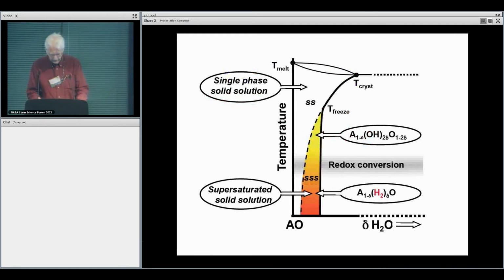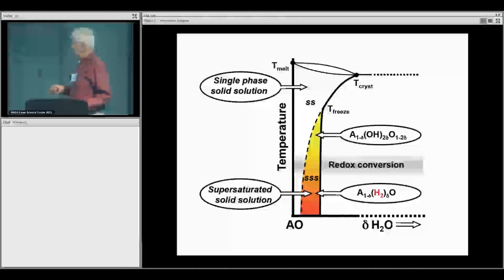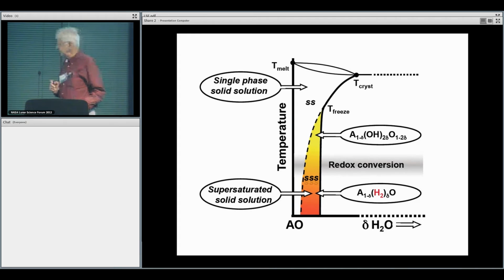Next slide, please. It shows that if you draw it in a phase diagram, you have a region where this redox conversion takes place around 500 degrees. Below this temperature, a fair fraction, probably in our laboratory experiment somewhere between 90 and 99% of the hydroxyl, disappears, for instance from the infrared spectrum, because they have converted into molecular hydrogen that at the beginning sits on interstitial sites. And down here, in the solid supersaturated as well as in the normal solid solution, you would have a modified chemical structure which would have to incorporate hydrogen. And the oxygen now is not all valence 2-; a certain fraction, namely 2 delta of this, would be in the valence 1-.